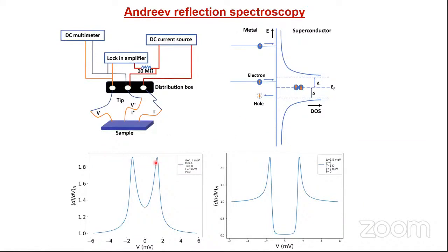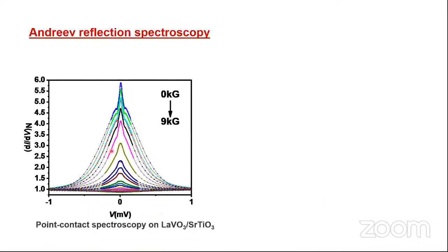And these are all for conventional superconductors, where the low bias conductance cannot be more than 2 times the high bias conductance. When we did these measurements, we found that the spectra did not look like the conventional Andreev reflection spectra. It did have some kind of peak structure here, but at 0 bias, we found a strong peak. In fact, with increasing magnetic field, we found splitting of the peak also, but we are doing more work on that. I do not want to talk about that now.